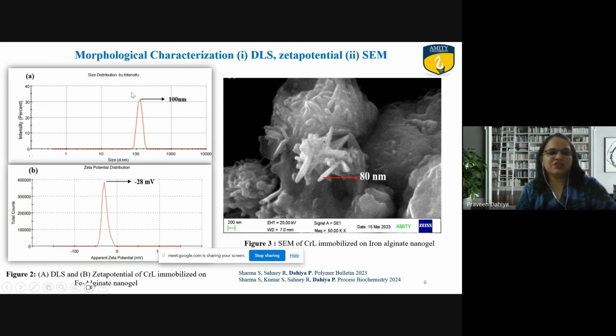The nanogels showed an average diameter of 100 nanometer and a zeta potential of minus 28 millivolts for immobilized Candida rugosa lipase, which indicated that they are more stable in the virgin coconut oil based system. Similarly, SEM images supported the elongated rod shape of the iron alginate nanogel with the size ranging from 80 to 90 nanometer. Morphological characterization thus confirmed the stability of these nanogels in the virgin coconut oil based system.